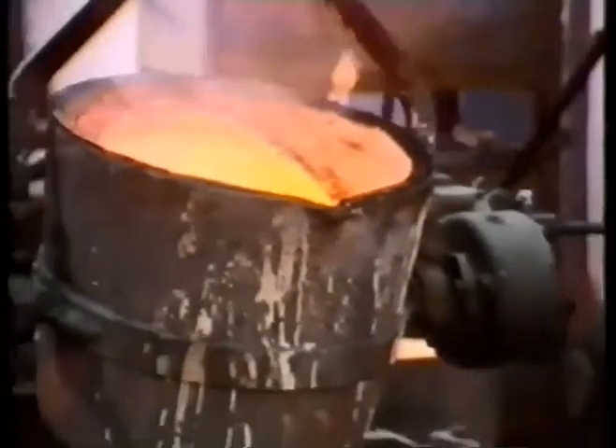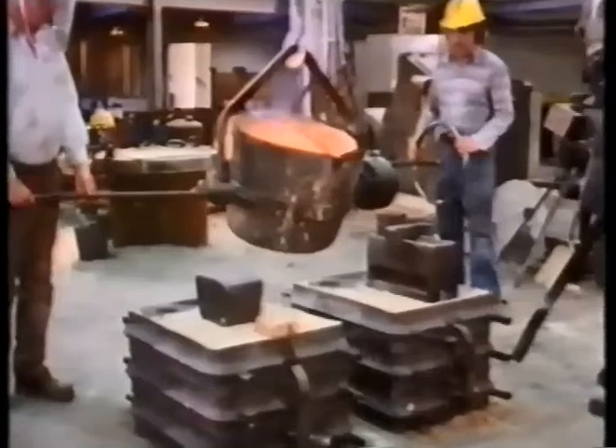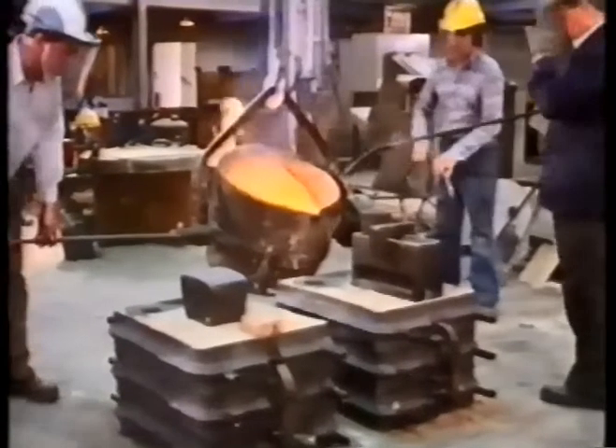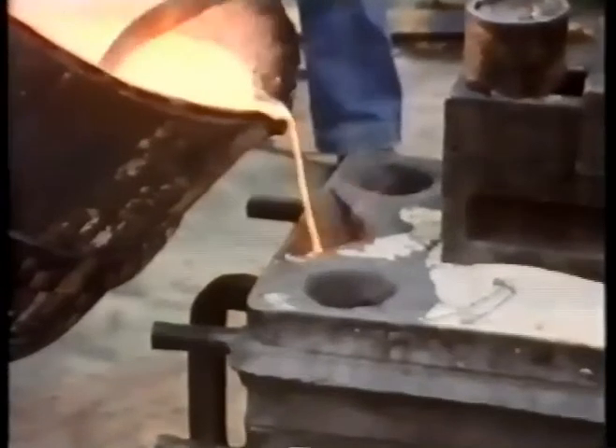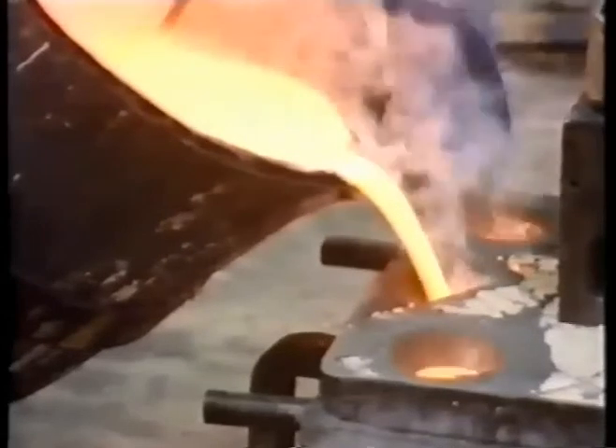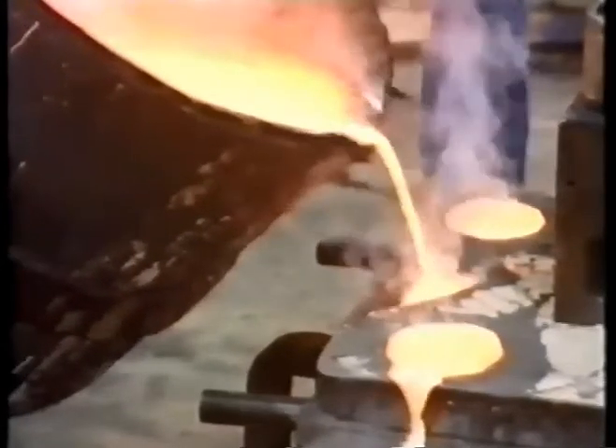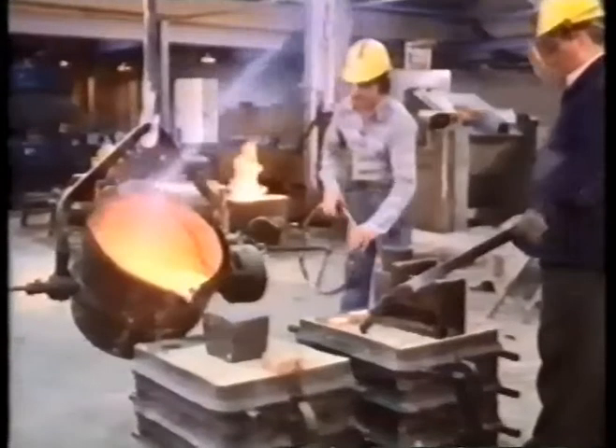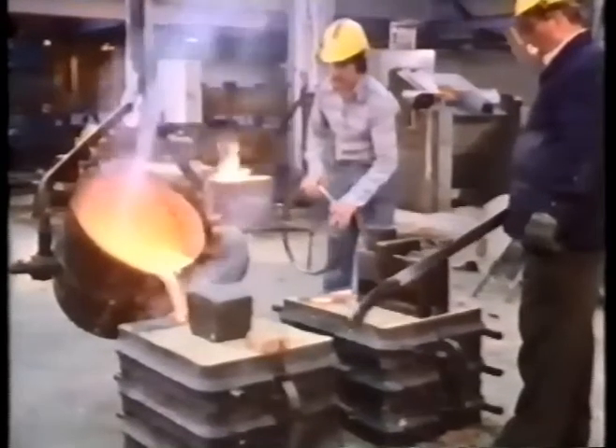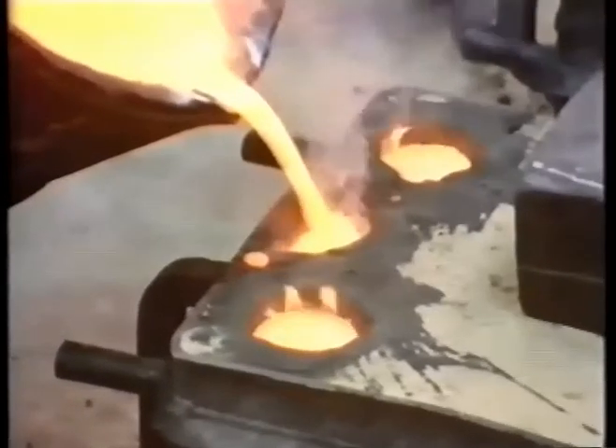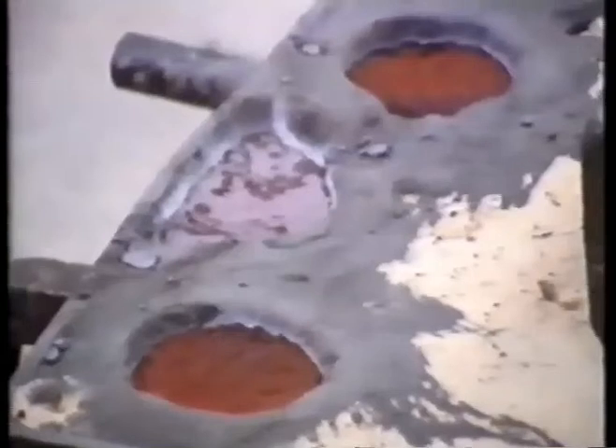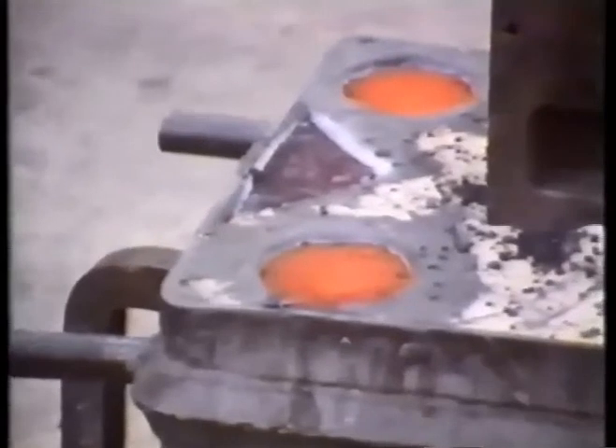On the right we have a completed mould without chills, and the metal is poured down the feeder tube and into the mould. When the mould is completely full, the excess material enters into the riser tubes, indicating that there is complete filling of the mould cavity. That was one without chills, and here's one which is exactly the same, but with the chills placed next to the running surface. A few minutes later, we can see that the risers in the chilled mould are cooling much faster than those in the mould box, which doesn't have any chills. There we can see the risers are still red hot.